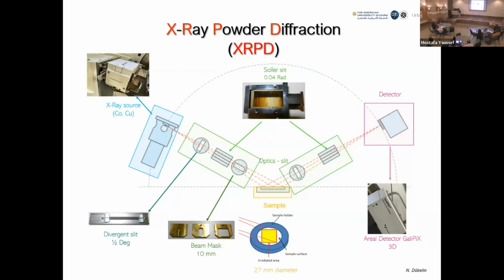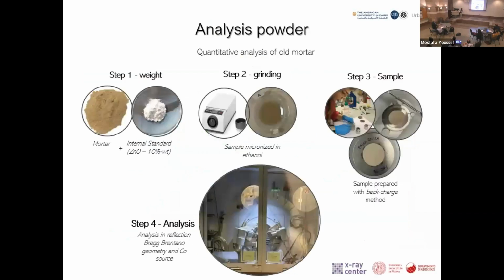And here I reported the main optical components that I used to do my analysis. To prepare the sample for the X-ray, if you want a good analysis, the way in which you prepare the sample is also important, because XRD works in a very detailed way if you are able to have a powder less than 50 micron. So what I did is just grind the old mortar and mix it with a small quantity of internal standard, because in this way I was able not only to obtain the mineralogical phases that belong to my sample, but also to quantify all of them.